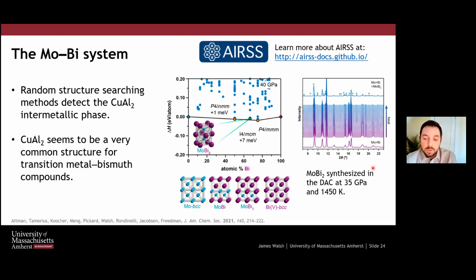And so what Alison found when she heated this was that the molybdenum bismuth 2 compound is synthesized. Again, it's an analog to the iron bismuth and the manganese bismuth. It seems like this copper aluminium structure type actually seems to be pretty common for transition metal bismuth compounds. We were also able to see that you get a lot of low energy structures that are basically BCC derivatives. So these two are probably not real ordered intermetallic structures, but it's showing us that alloys are perhaps stabilized, and we actually do see evidence in the diffraction that alloying seems to be present.